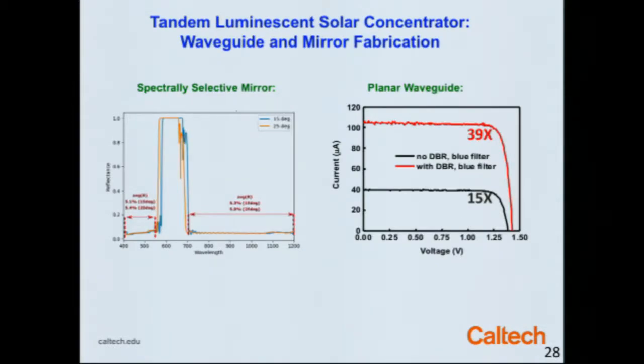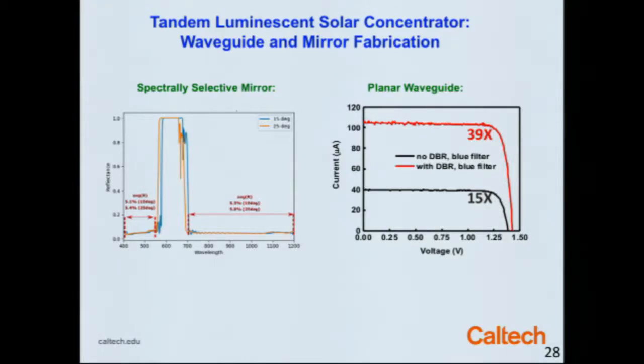And if we work on more optimally designed mirrors—this one has a reflectivity of 99.99%, a simple Bragg reflector, illustrating how effective Bragg reflectors can be. The other interesting thing is this Bragg reflector has about a 3 or 4% reflectance out of band, where you don't want it to reflect. As a result, we've been able to get to a record efficiency of almost 40 times.